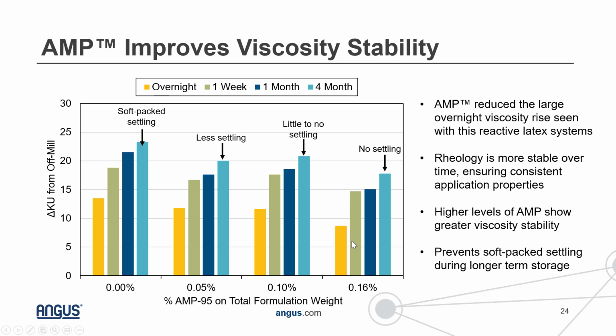that contain AMP, especially with a latex like this, which is capable of forming latex pigment composite particles. That has a very significant influence on viscosity. And so the ability of AMP to really reduce that viscosity rise seen over time can be very useful for these types of formulations. We also noticed that after a longer term